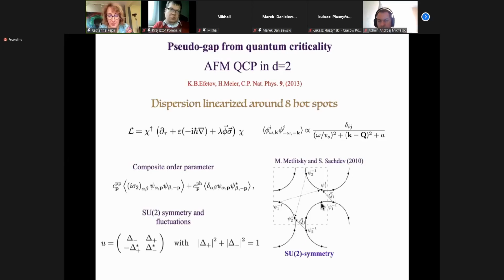And see here the Fermi surface of the cuprates, and here is the antiferromagnetic zone boundary. So when they cross, you have what we call hotspots when antiferromagnetism is big, and electrons can see it even at 0 temperature. And around these hotspots, if you look at the model with simple interaction, the SU2 symmetry is exact. In D equal 2, you have particle-particle and particle-hole pairing formation, and they are completely degenerate. Namely, you can rotate from one to another, and the order parameter that is forming and gives rise to non-zero value for the sum of the 2 amplitudes is a superposition of the 2 order parameters there.